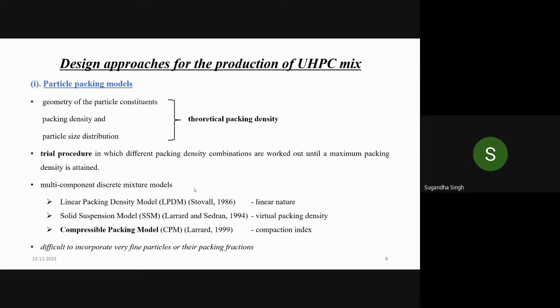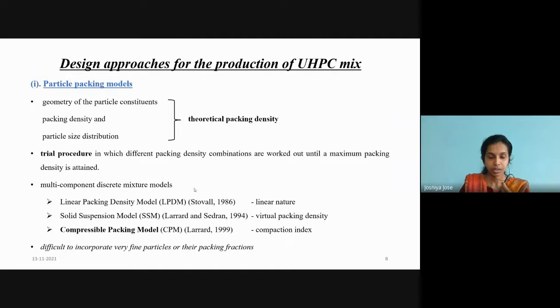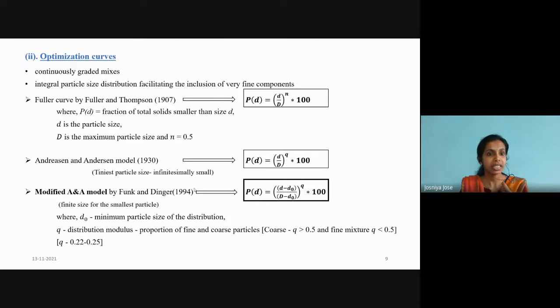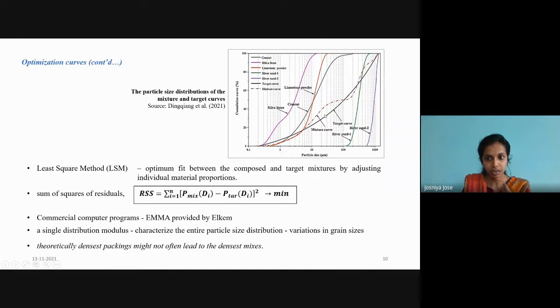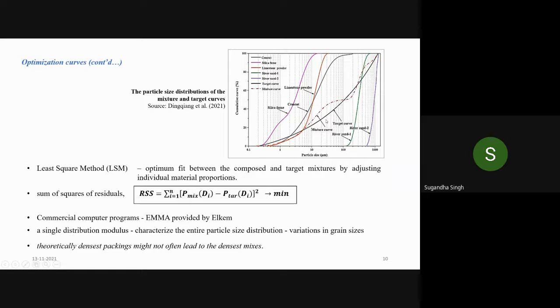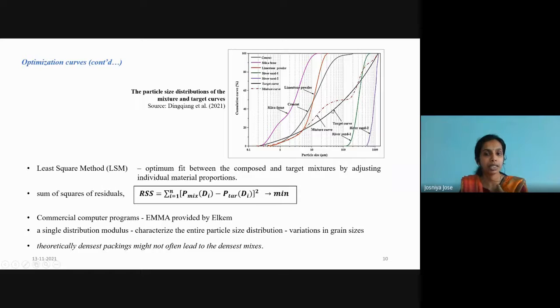That's a statement from one of your slides, right? Okay, ma'am. Usually, researchers have used this modified Andreasen and Andersen model. So they will be fixing a value of distribution modulus so that they will be obtaining a target curve. Right. So individually, by trial and error method, we'll adjust the proportions of each of the constituents in order to decrease the variation between the composed mix and target curve. So if this mixture curve properly matches the target curve with the least deviation, we can say that it's a properly compacted mix.